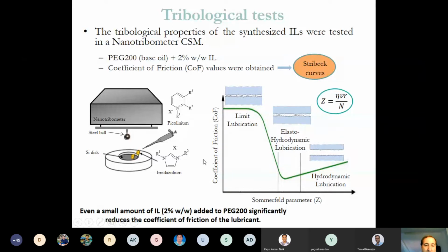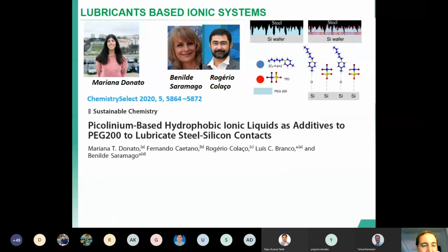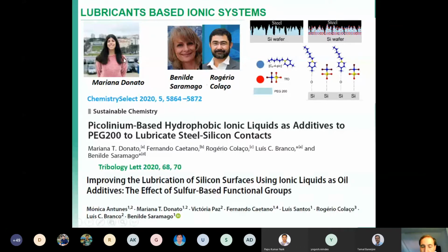And we proved, using imidazolium cations and picolinium cations, that a small amount of ionic liquid, only 2%, added to polyethylene glycol significantly reduces the coefficient of friction of the lubricant, and this is very attractive for this kind of applications. And recently, in 2020, this year, we already published the picolinium-based hydrophobic ionic liquids, these methylpyridinium cations, as additives to polyethylene glycol, PEG 200, to lubricate steel-silicon contacts. This was done in the PhD thesis of Mariana Donato, and it's also possible to improve the lubrication of silicon surfaces using ionic liquids as oil additives.